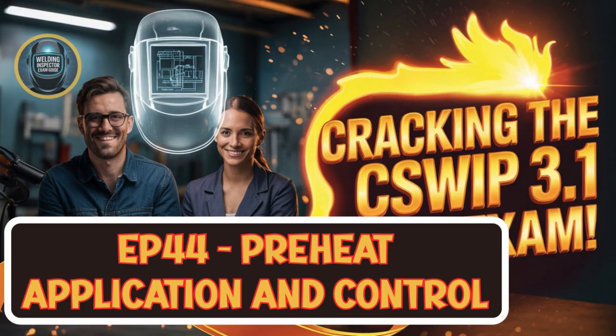Makes sense. Precisely. Plus, another benefit. Preheat also effectively removes moisture from the weld preparation area. Gets rid of water beforehand. Yeah, and moisture is a big source of hydrogen in the first place, so drying it out is a huge plus. And beyond that, preheat actually improves the overall fusion characteristics when you're welding, and it helps ensure more uniform expansion and contraction. Uniform expansion, meaning less stress. You got it. That uniformity lowers the internal stresses that can build up between the weld metal and the parent material. It makes for a much more robust, less stressed joint overall.